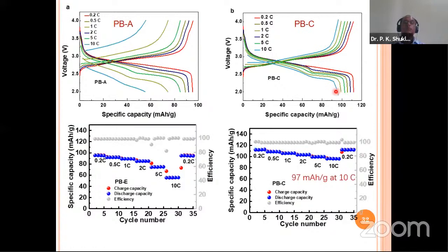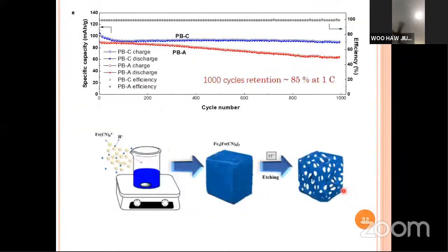And this is the cycling result. If you look at here, for 10 C rating, we obtain 97 milliampere hour per gram after 35 cycles. Much improved result compared to our 2 previous systems. And this is for long cycles, over 1,000 cycles retention. We retained 85% of the capacity at 1 C rate, okay? And this is a schematic diagram of the Prussian blue acid etching and double heating.